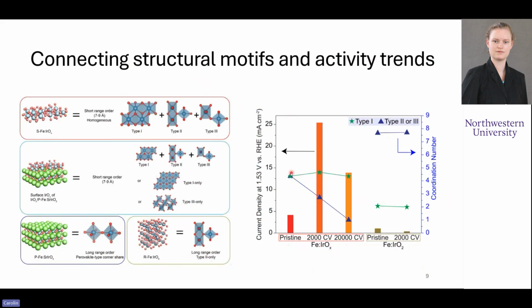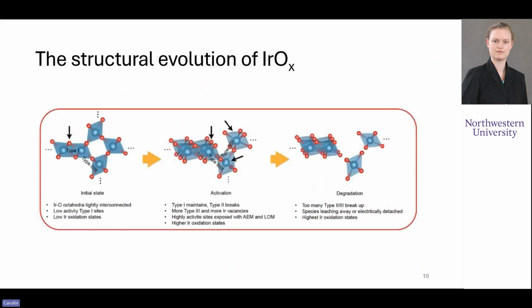But our iridium oxide, you can see that connectivity drop over time as that catalyst is used. So it seems that these type 2 or 3 connections seem to kind of be less stable and break apart as that catalyst is used, and that contributes to both its activity and how it degrades. So having learned all of those parts, we can now summarize the structural evolution of our iridium oxide.